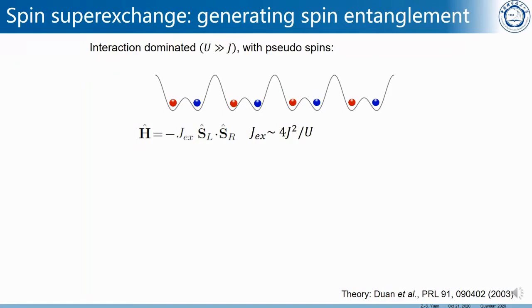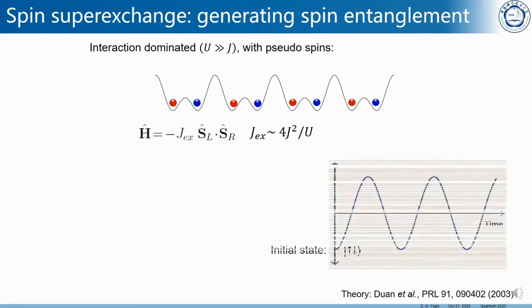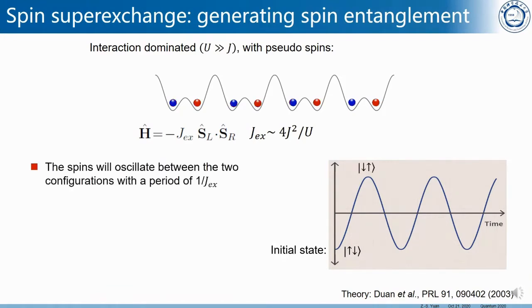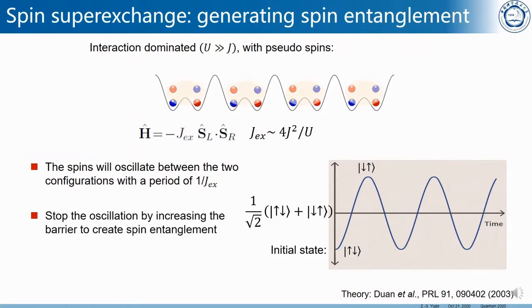We apply a superlattice to divide the atoms into double wells and flip the spin of every second atom. Then we prepare the initial state of spin up and down in each double well. As these spin configurations are not the eigenstate of the system, the atoms will oscillate between these two spin configurations. And if we stop at half of the way, we will create the spin entangled state.